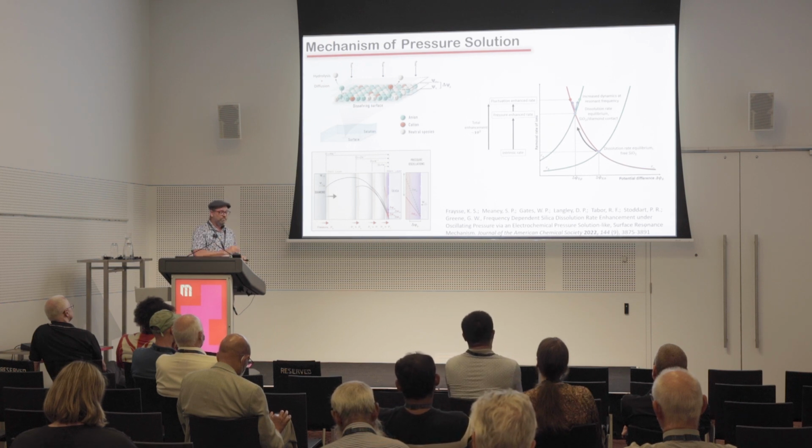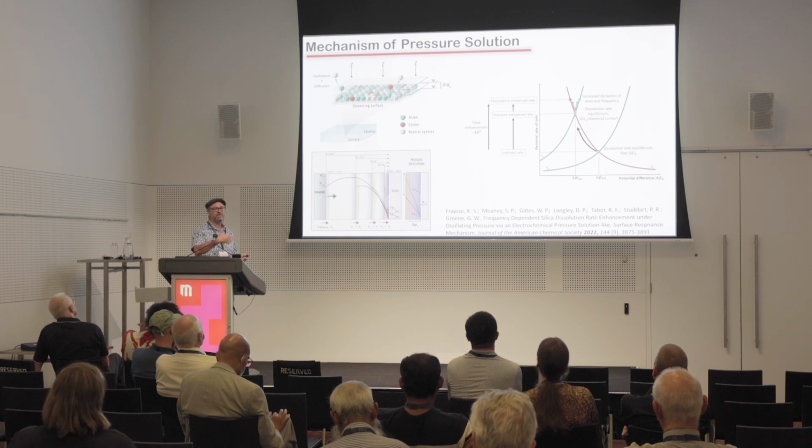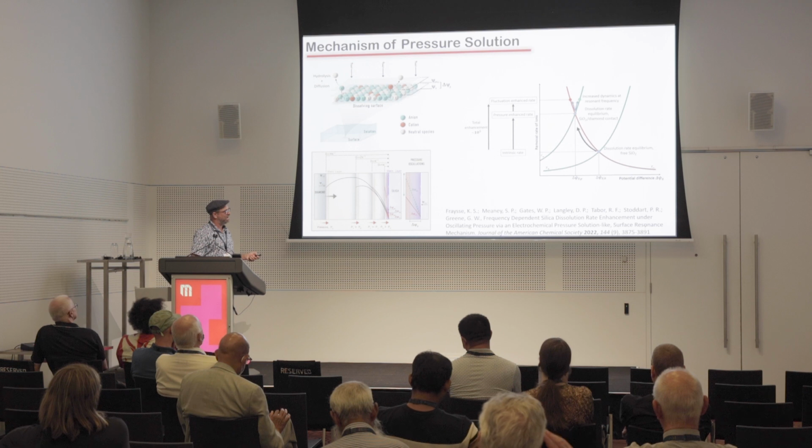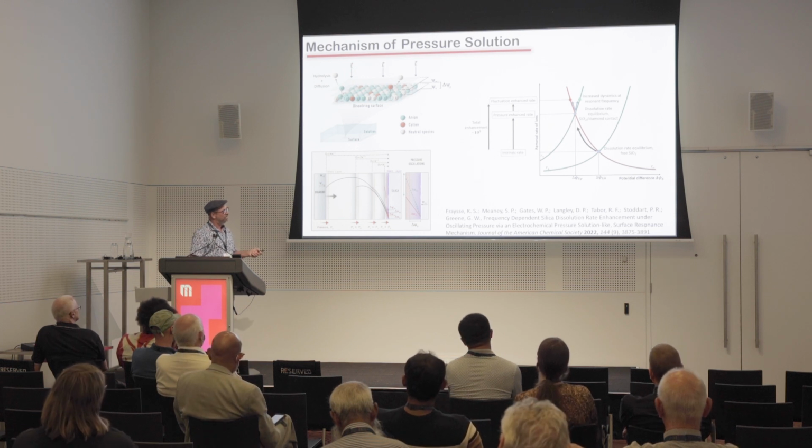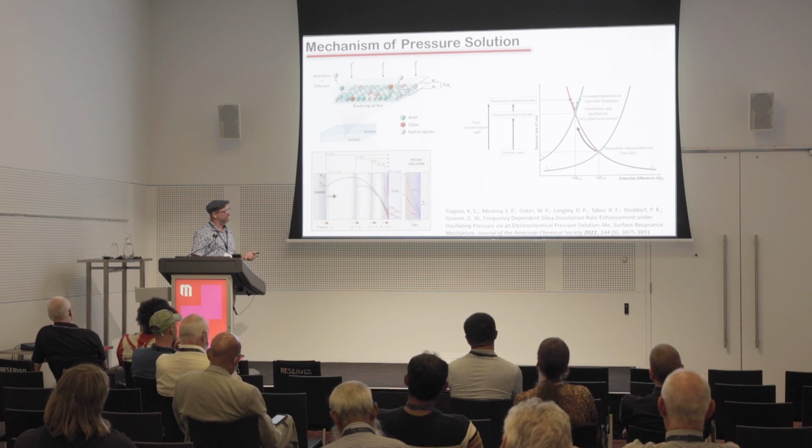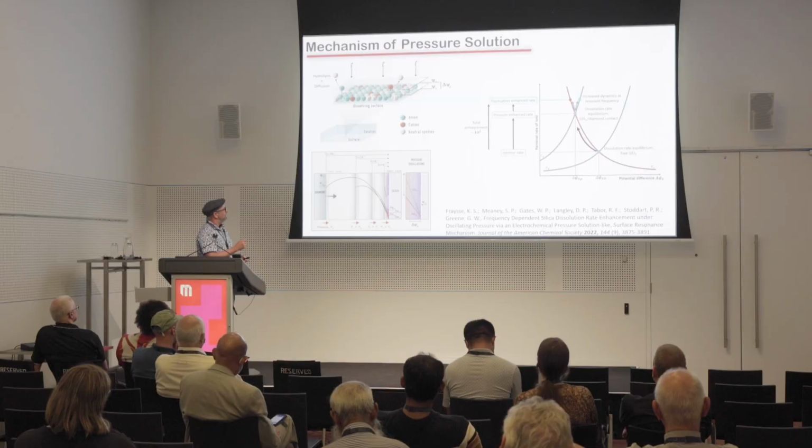Now, because silica charges negatively, the electric field generated by that silica surface will actually enhance the rate of dissolution, or the removal of the anionic charge, and it will suppress the removal of the cationic charge. And so the equilibrium Stern potential that you observe is actually the point at which those two processes are in stoichiometric equilibrium.